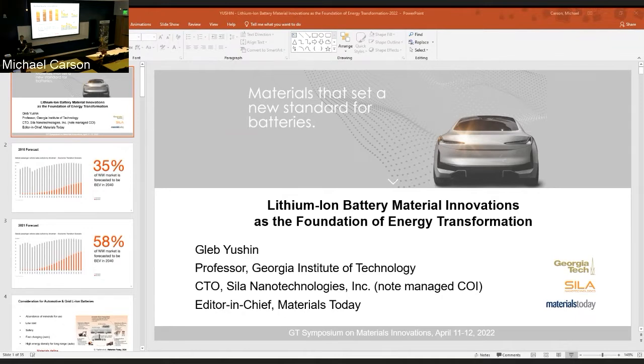And so we predicted that by moving to silicon chemistry, and we assume, let's say by 2030, the price for high-performance lithium-ion batteries will be reduced below $75 per kilowatt hour. And now I think that these predictions are even conservative. And this is because there are multiple components that contribute to the pricing. There is manufacturing of lithium-ion batteries, there is cost of inactive materials such as casing, electrolyte, separator, foils, and then there is also the prices of the active materials, cathodes and anodes.